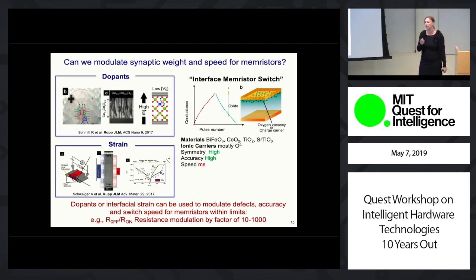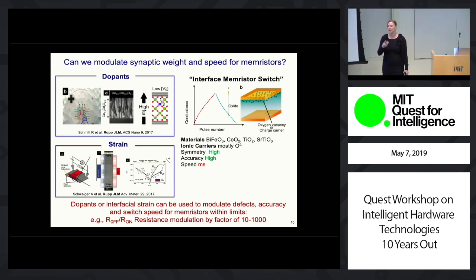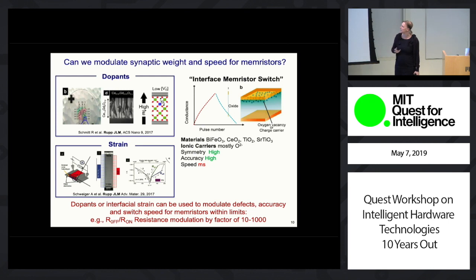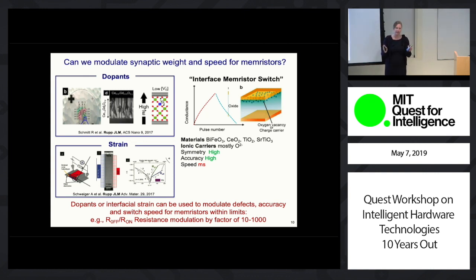So the most classic thing you could do is take, for instance, defects and manipulate the defects either by extrinsic dopants or strain. That has also been done in electronic transistors. There are various examples. But to be very honest, even though I have also published in those, there's a certain extent to which you can change the resistance values or the dynamics, but you will be limited, for instance, on the resistance modulation, at least by a factor of 10 to 1,000, whatever I can dope in the material classes I showed you before. So there's a certain range I can manipulate, but I can't go beyond that.